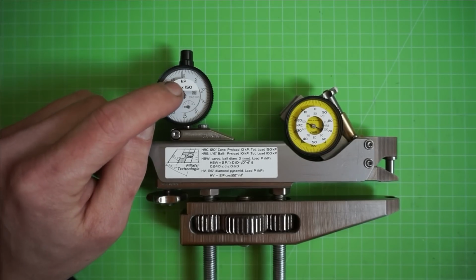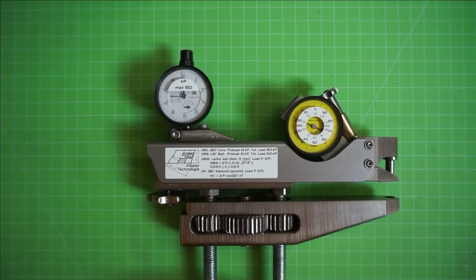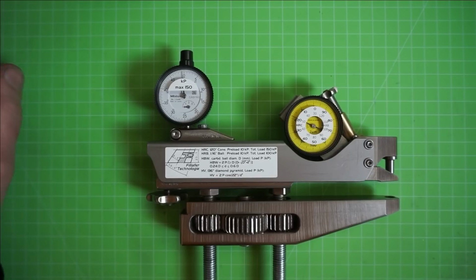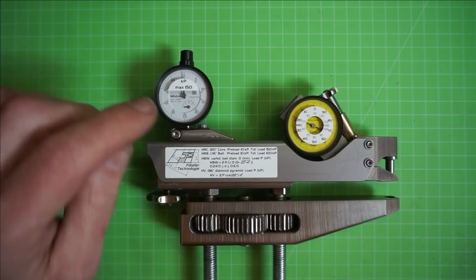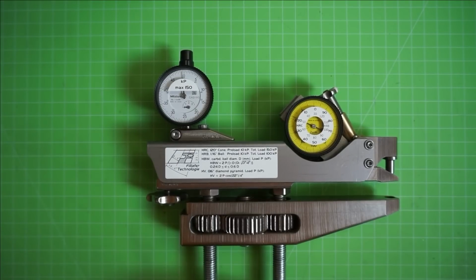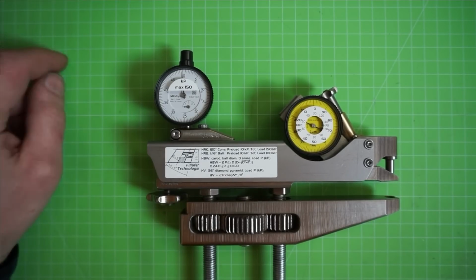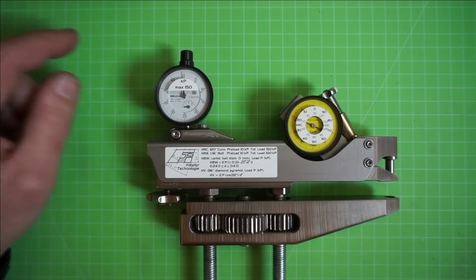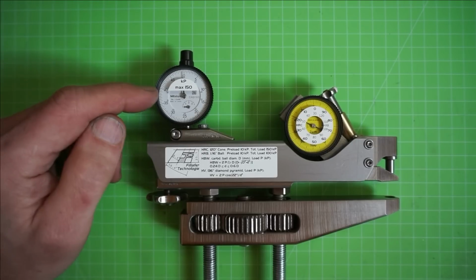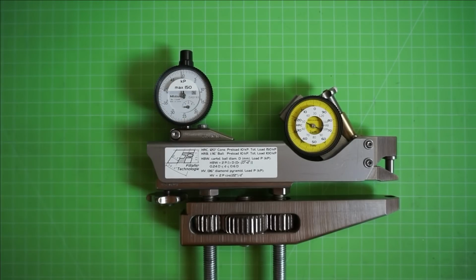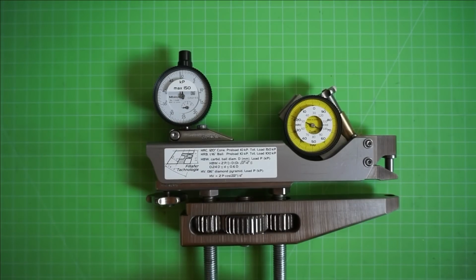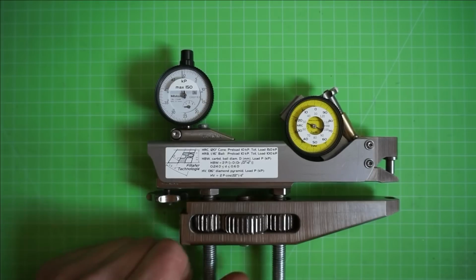I have kiloponds here, even though it is not used anymore, because the definition for all the hardness testing methods is done historically in kiloponds, so we have round kilopond numbers. Now the current ISO standards have 1400 and something point something newtons, but I'd rather work in round numbers, which is why we have the kiloponds here. For Rockwell, for example, we use 150 kiloponds testing load, and for the other tests we use either 10 kiloponds, 50 kiloponds, depending on which method you're using.